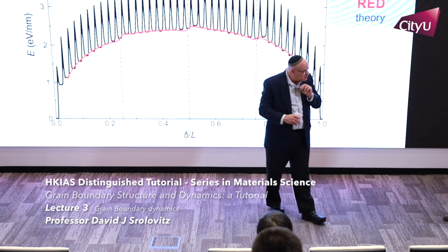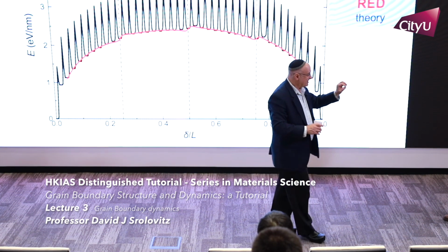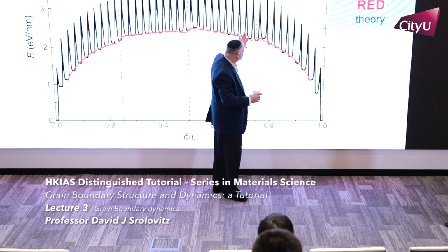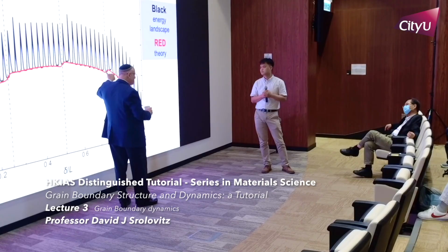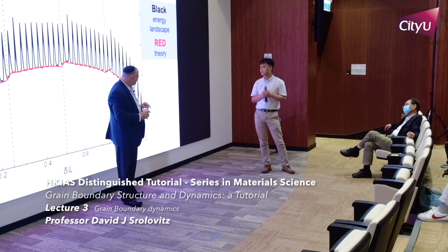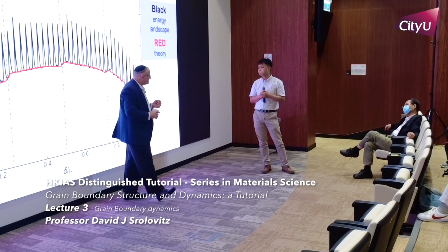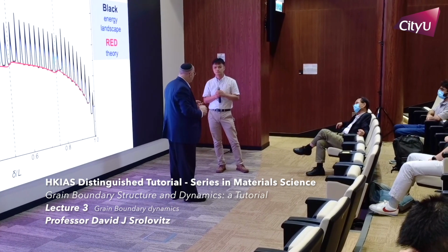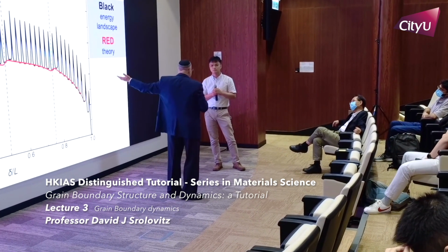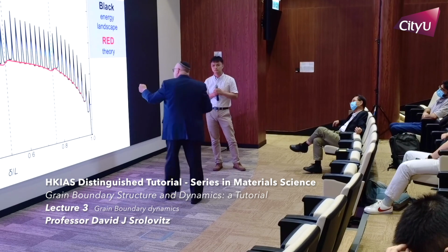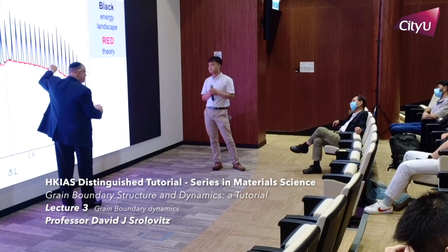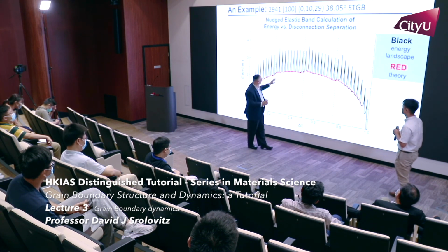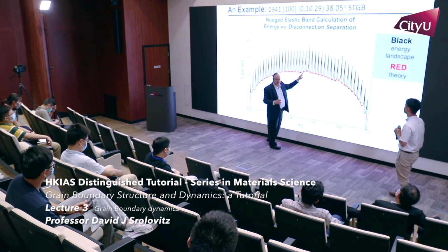And now if I go to something which is really sigma infinity, that just means I still have a curve that looks exactly like this one, except I don't know where those bumps are because they're not periodic. So sigma as a measure of the properties of a boundary, it's crazy. This boundary is just a sigma 5 boundary with these little differences, because everything from here to there is sigma 5.